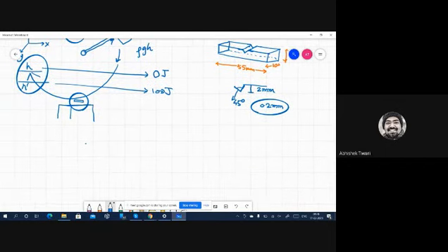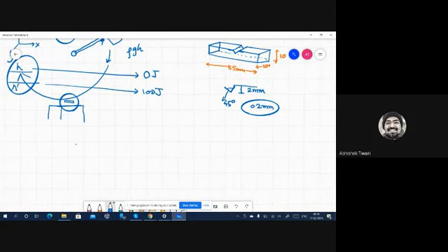Again, we can bend the rules a little bit because we have practical reasons. Sometimes the material is not available, and sometimes you cannot make the material in so much amount that you can make a specimen of this dimension. So you can do miniature testing. There are sub-size Charpy tests where usually the dimensions remain 55 by 10, but you can decrease the thickness to 5 millimeters. Sometimes you can decrease the thickness to 2 millimeters also. There have been trials where people have actually decreased these dimensions also.